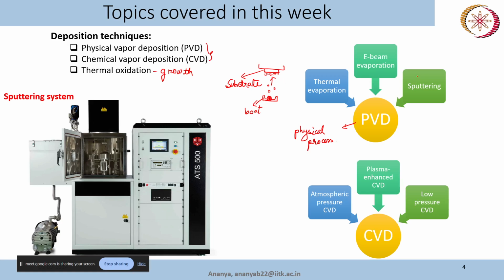Now sputtering is a bit different compared to thermal evaporation and e-beam evaporation. What happens here in case of sputtering is that we create a plasma between our target and our substrate. So this is our substrate, and this is the target. Now I introduce a gas between these, typically argon. This argon will become argon plus and an electron, and we apply negative bias to the target. So the argon plus ion will come here and hit the target and eject some atoms from the target, and those atoms will sit at the substrate. Okay. This is the basic of the sputtering technique.